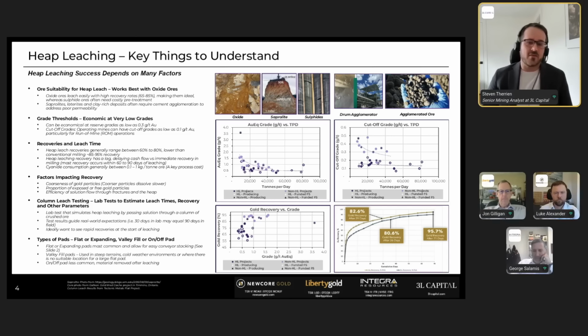So you can get factors such as the leachability of the metal, the recovery rates, the leach kinetics, so the rate at which the gold dissolves, the reagent efficiency, how much cyanide is being consumed, and stability. So how much compaction you're getting when you apply this solution. If you get too much compaction, you can start to form channels through the heap leach, and then that solution is not flowing nicely through the heap, and you would potentially get lower recovery if that happened.